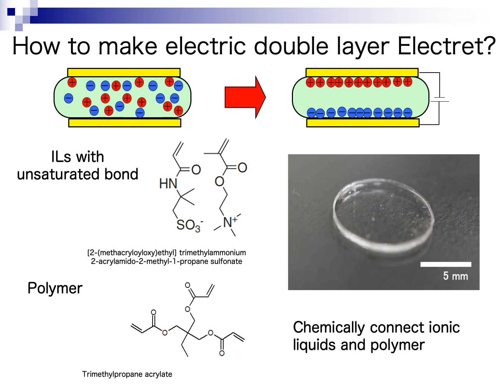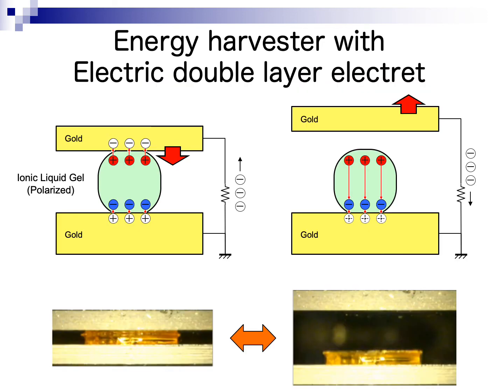Using this electret, we are going to fabricate a vibration energy harvester. We sandwich the electret with two electrodes, and when we attach and detach the electrode, electrons are induced at the electrode. Since the capacitance of the double layer electret is huge, a large current is accumulated at the surface of the electrode.